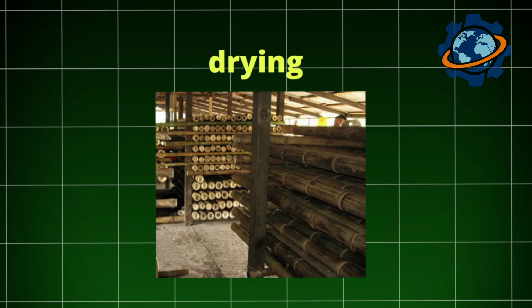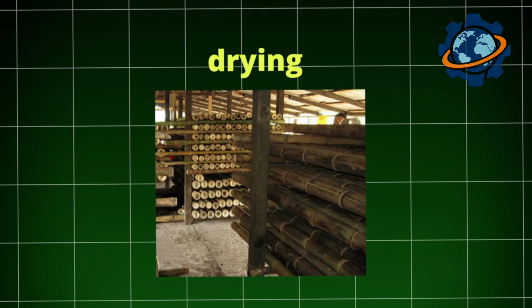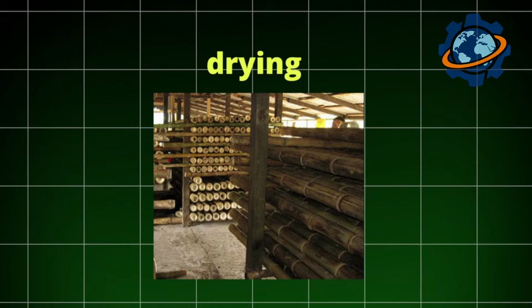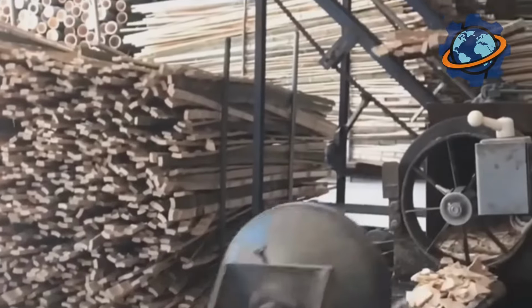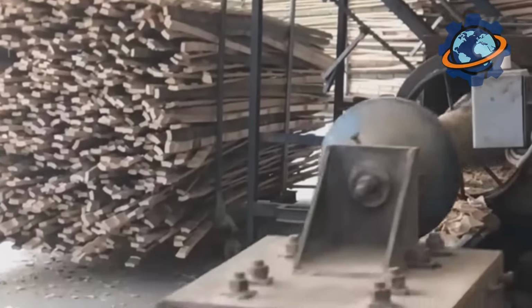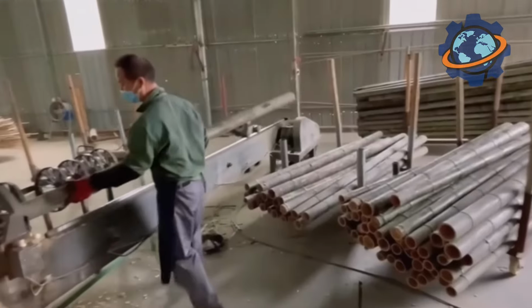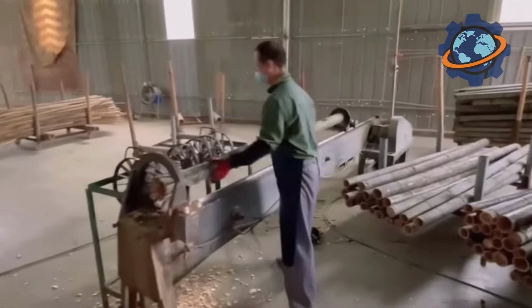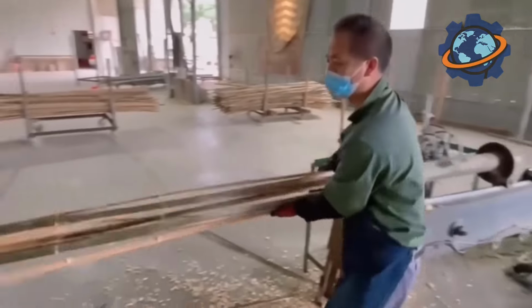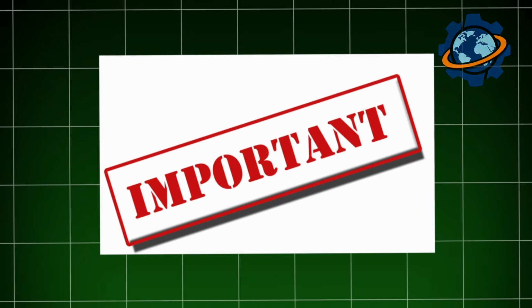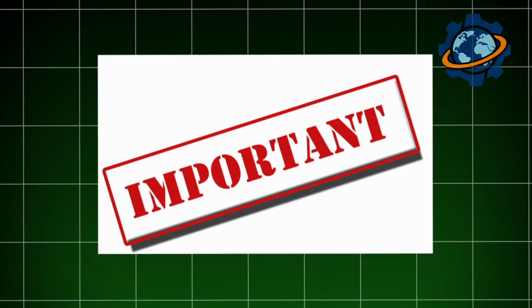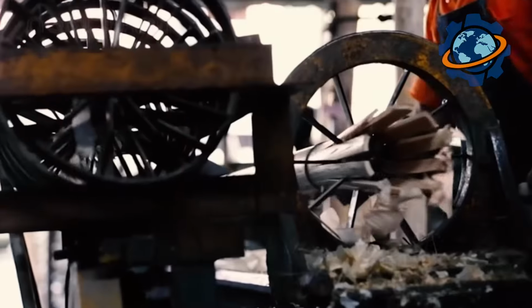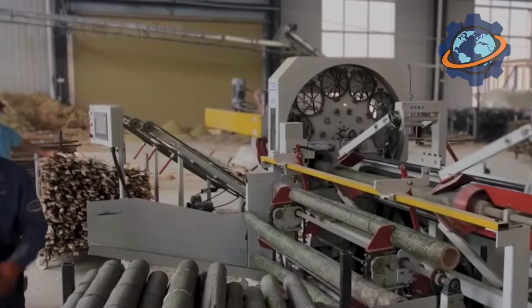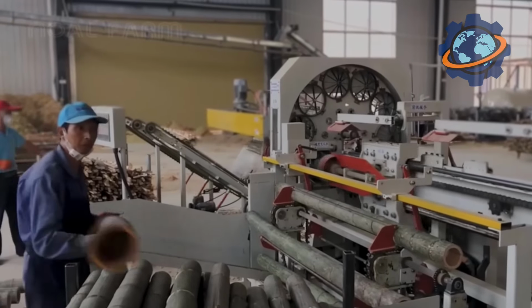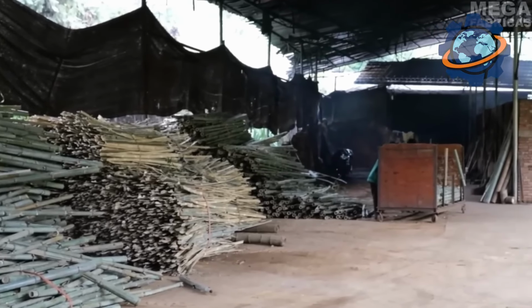After this, the planks are sent for drying. Some producers dry them in the open air, but for industrial scales, they are loaded into giant kiln dryers, where they spend several days until their moisture level drops from 50% to an ideal 8 or 10%. This stage is critically important, as any residual moisture can lead to warping and cracking of the finished product. But the journey from a 60-foot pole to a smooth floorboard requires even more impressive engineering.